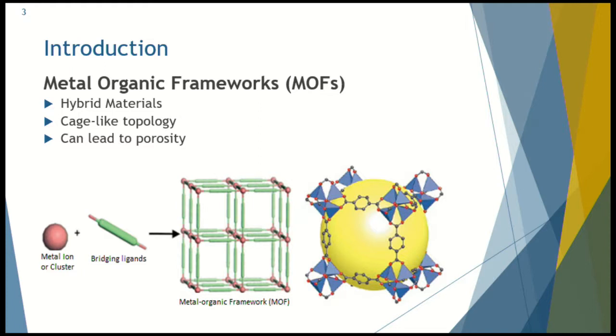Right? The network connectivity of these materials tends to lead to materials that are often porous. As you can see here, you can have spaces and channels within the framework, and this is actually a crystal structure of a MOF with zinc oxide metal clusters with terephthalic acid linear linkers. And the yellow sphere here just shows you the pore or the space within these frameworks.